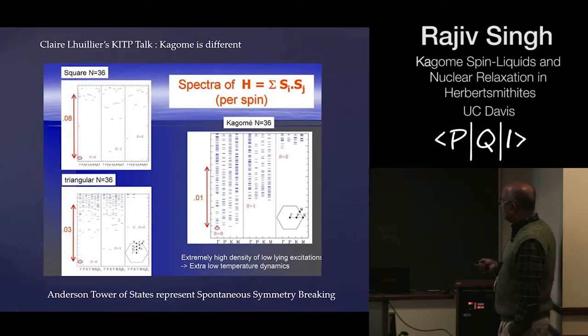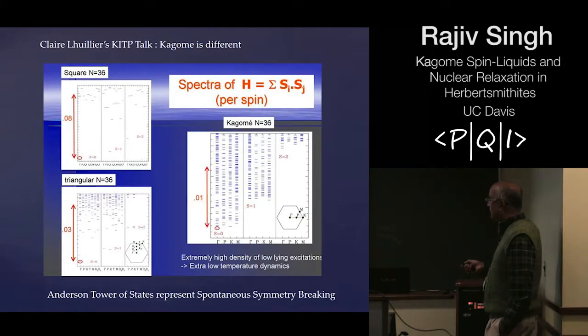and much of the information about quantum spin liquid really comes from looking at the spectra of finite systems, and you can see the clear difference between say a square lattice, a triangular lattice and a Kagome lattice by just looking at the spectra of 36 site. So for example, this is the square lattice. One can see the sparsity of the spectrum over here. On this energy scale, they all have a J of 1. On this energy scale, there are very few states over here, and on this axis we have different quantum numbers of the system. So this is S equals 0, S equals 1, S equals 2, and the momentum quantum numbers are labeled over here, which one does not need to read really, and on this axis is the energy.